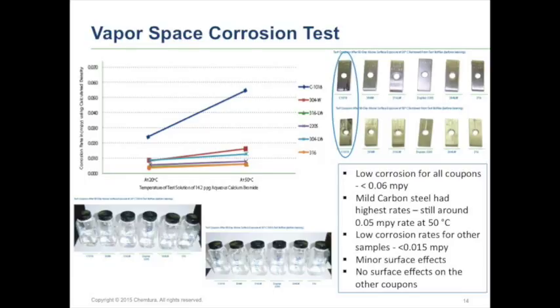Looking at the vapor space, this is basically no corrosion whatsoever. These limits are incredibly low, even across the board for carbon steel. The solutions picked up absolutely no color, and basically all the coupons for the most part look very clean. So when you're looking at the vapor space, it's really not the vapor at these temperatures that you're having issues with. You're not creating a lot of HBr out of the solution that's going to impact where the vapor is coming in contact with the metal.